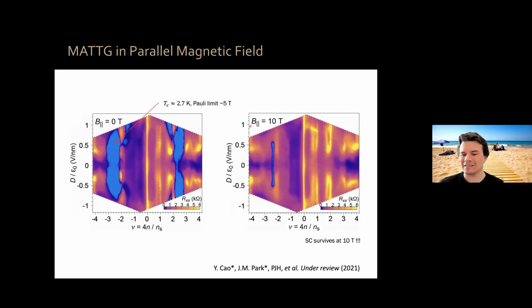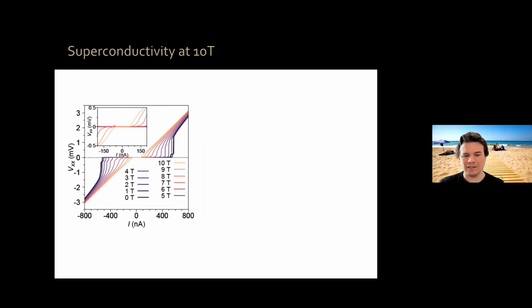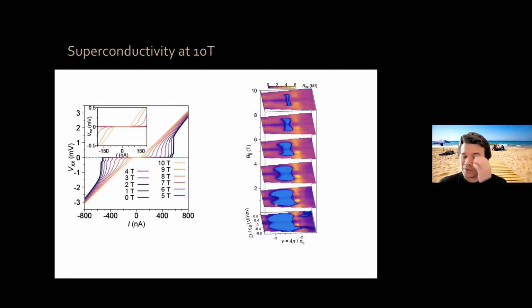Well, we measure at 10 Tesla parallel field, our superconductivity is still present in the region of optimal doping, okay, over a broad displacement field, okay? In fact, I can show you the VI traces so that you can see that this is indeed robust superconductivity all the way to 10 Tesla and beyond, okay? You can look at these zoom-ins of this phase diagram in filling factor and displacement field at different parallel magnetic fields, and you see that superconductivity gets suppressed gradually, but it still persists at fields beyond 10 Tesla.